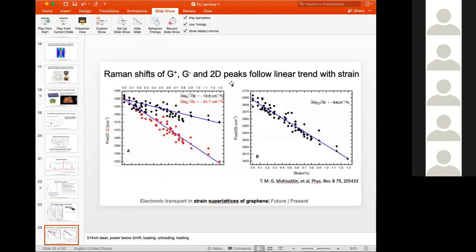So physically, the Raman shift is decreasing because the Raman shift is calculated as a shift in the peak positions, right? And the peaks originate themselves because of lattice vibrations. So if you have a certain amount of strain generated in the system, the atoms, the lattice is going to vibrate differently because of the strain. And so the peak positions change because of that. And that is why there is a strain dependence of the Raman shift. Does that make sense for the first part?